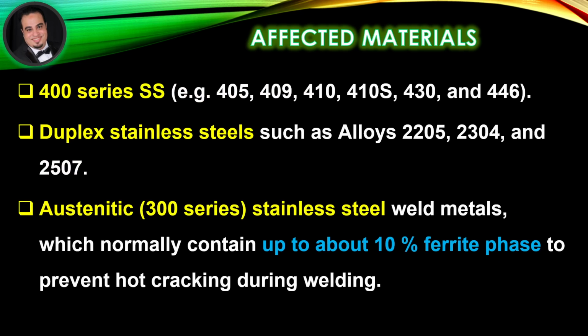Affected materials. 400 series stainless steels. Duplex stainless steels. Austenitic, 300 series, stainless steel weld metals, which normally contain up to about 10% ferrite phase, to prevent hot cracking during welding.